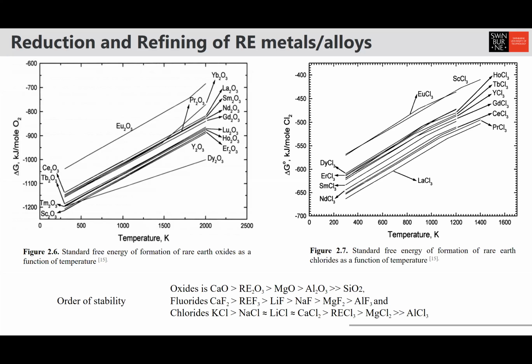But in chlorides, KCl, potassium chloride, sodium chloride, lithium chloride, calcium chloride, they're actually more stable compared to the rare earth chloride. So that's why chloride-based high temperature processing to process these rare elements is more suitable compared to when we're dealing with oxide there.